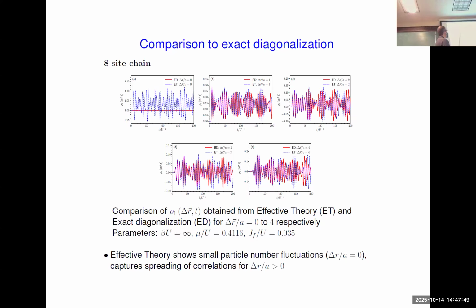But yeah, we have agreement at about the 5 to 10% level in terms of the number of particles per site. If we go to delta R equals 1, 2, 3, 4, you can see that we capture the phase of the single particle density matrix pretty well out to, at least for the first set of oscillations and maybe even more, depending on delta R. And the amplitude is not bad as well, at least at this particular value of parameters that we used.